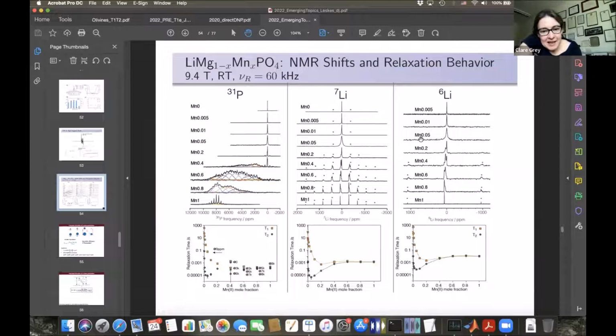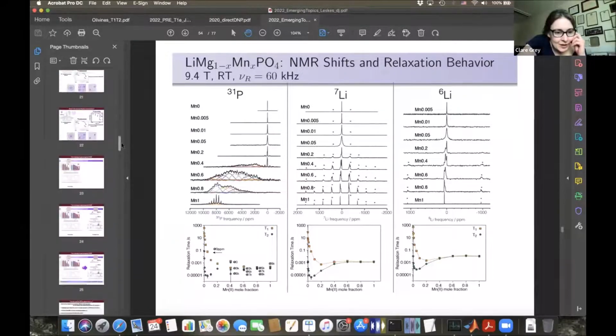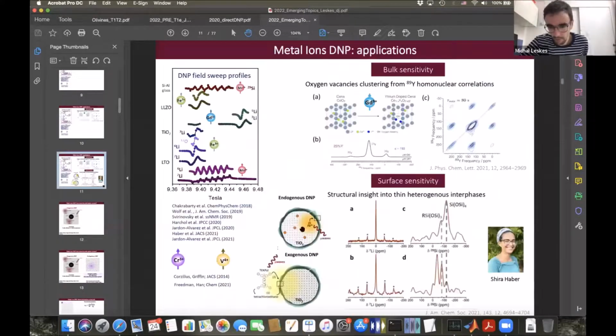That's really nice. And in some of the lithium DNP work we've been doing, we've looked at the enhancement of the junk on the surface. Did you ever see any evidence of polarization from the manganese to any junk or carbonates on the surface, like any of the 0 ppm peaks? Was there any evidence for enhancement? Yeah, in this work that Shira did, the idea was to try both things, DNP from outside in and from inside out, and in both cases she was able to enhance, so the coating of this material was okay. Now the next step would be to be more quantitative about this: how far are we going outside and how far are we going inside?